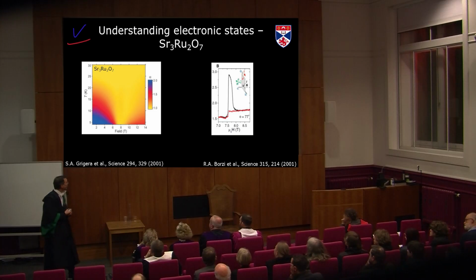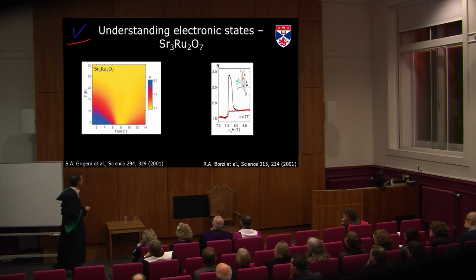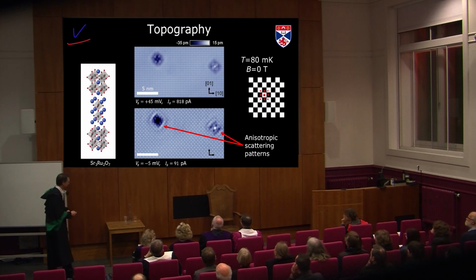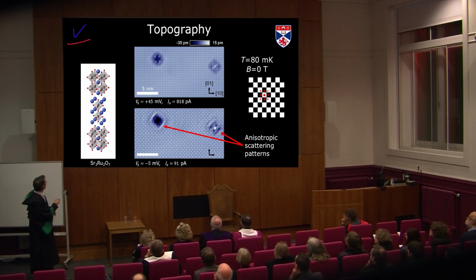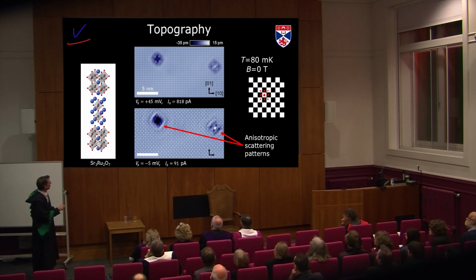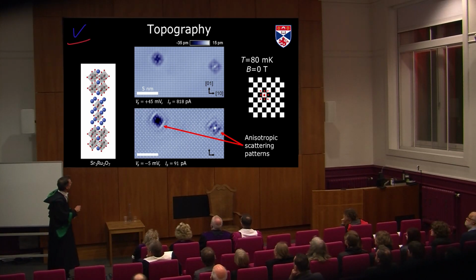but it wasn't understood why that's happening. So we thought, well, that's an ideal thing to study with our microscope, so we put one of these samples into our scanning tunneling microscope. Here's how it looks. This is the crystal structure. We break the samples in this place between the strontium atoms. This is the strontium square lattice. You've already seen such an image, and two defects here.